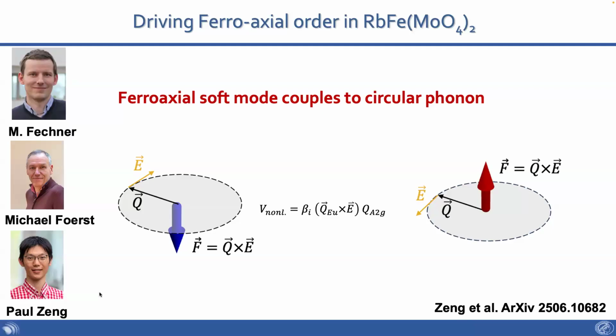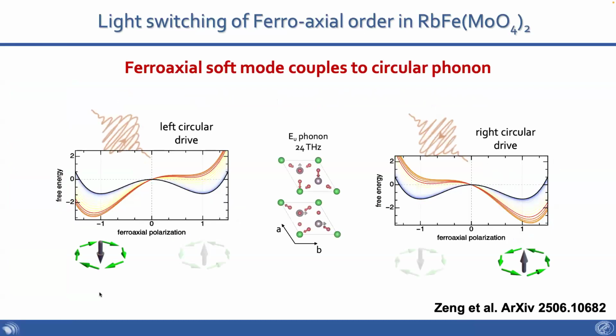So anyway, basically, if the ions are rotating in circle, this engineered field, Q cross Q dot, will either be positive or negative, depending on which direction the phonons are rotating. And there will be a nonlinear coupling between the ferroaxial mode and this cross product of the two. So you can calculate the equations of motion of this. This used to be my ferroaxial order as a function of the amplitude of the A2G mode. Now I apply this high frequency bias with a circularly polarized light field and the Q cross E of that field. So this is the doubly degenerate mode that I'm driving in circle. It's an EU mode, of which there's two. So I can engineer a field that rotates. And now this will apply a force which will displace and tip this otherwise degenerate pair of states either to the right or to the left. And so this is basically an engineered axial field that couples to the ferroaxial mode.